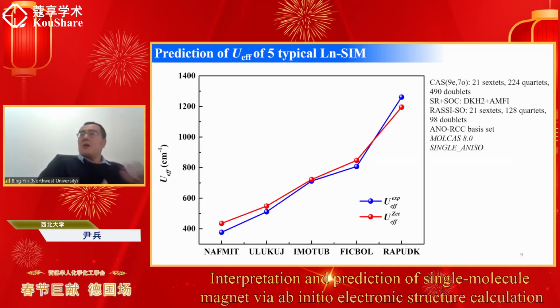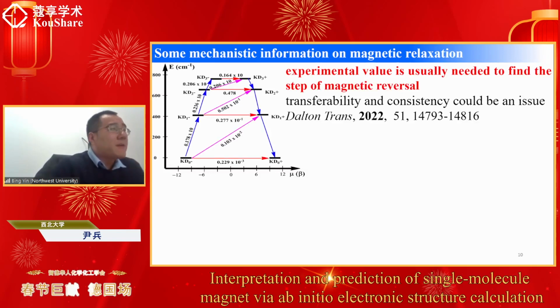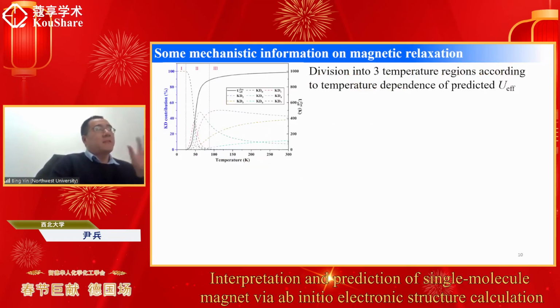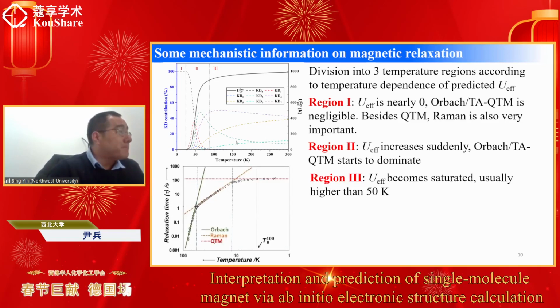So besides the predicted parameters, we can also give some mechanistic information on magnetic relaxation. For example, based on our method to calculate the energy barrier, we can divide the temperature range into 3 parts according to the temperature dependence of the predicted energy barrier. In region 1, the energy barrier is nearly 0. That means the thermally activated pathway is negligible. And in this region, QTM and Raman are very important.